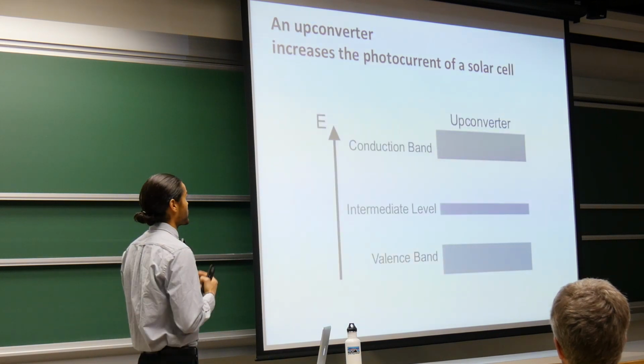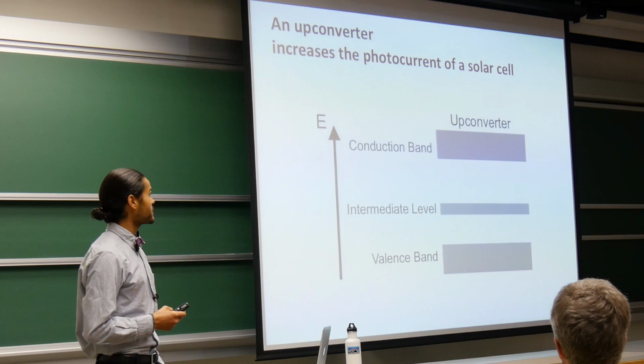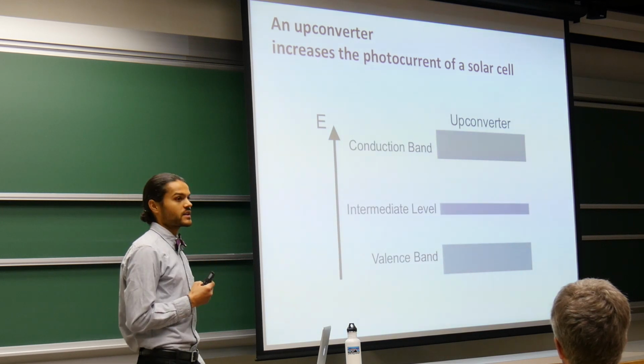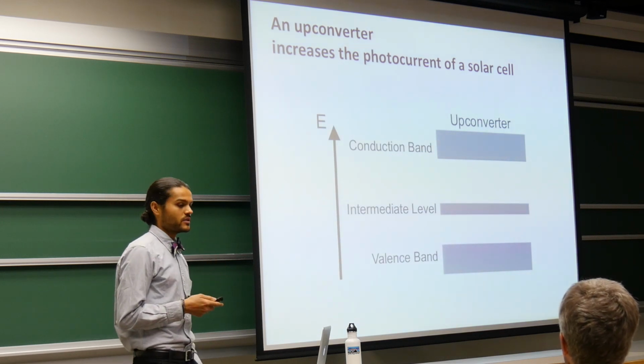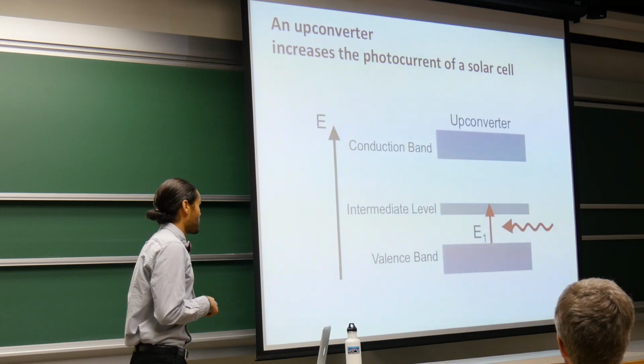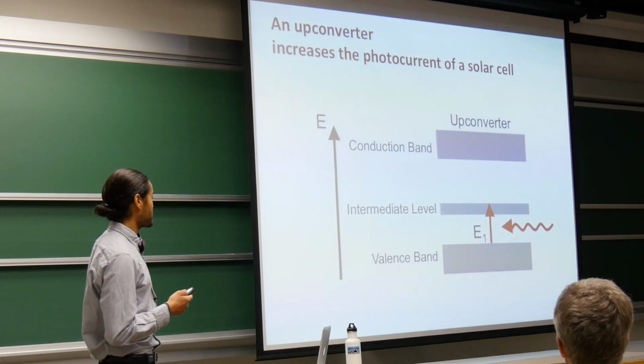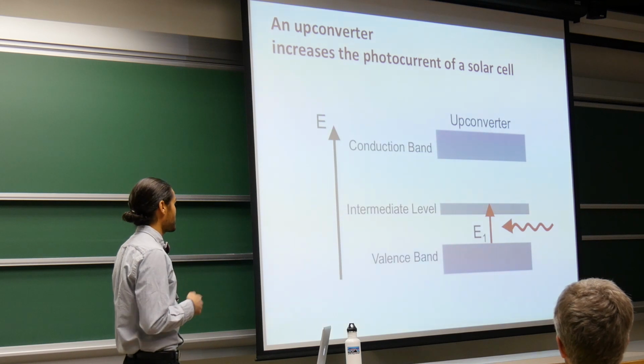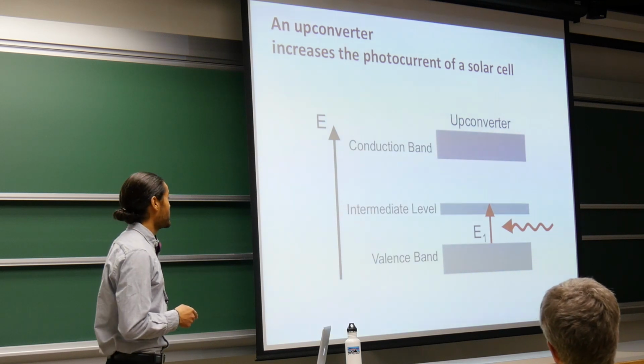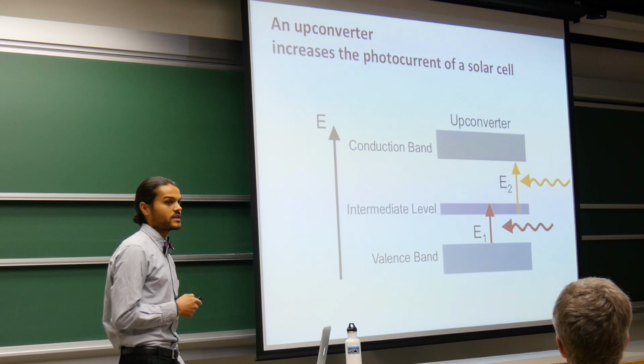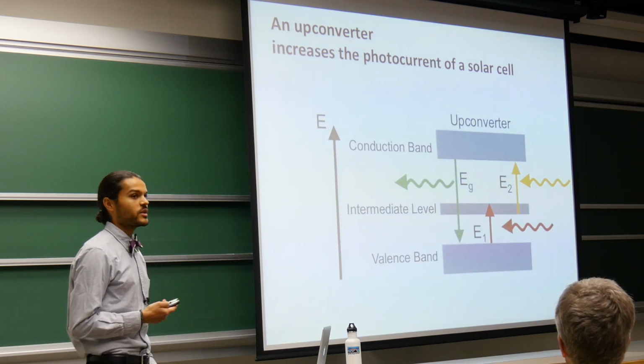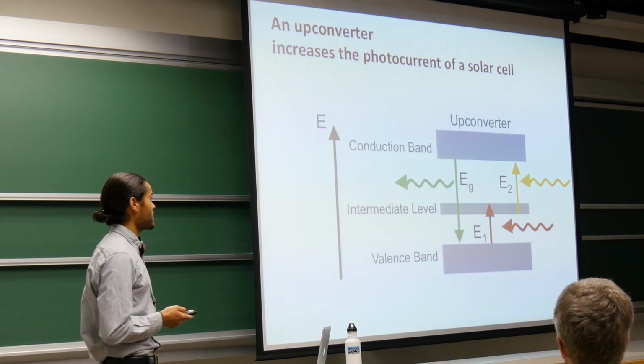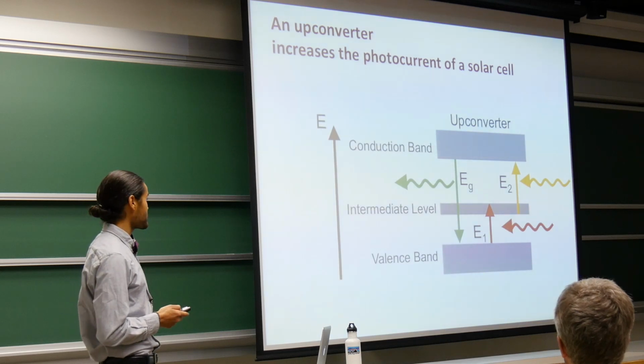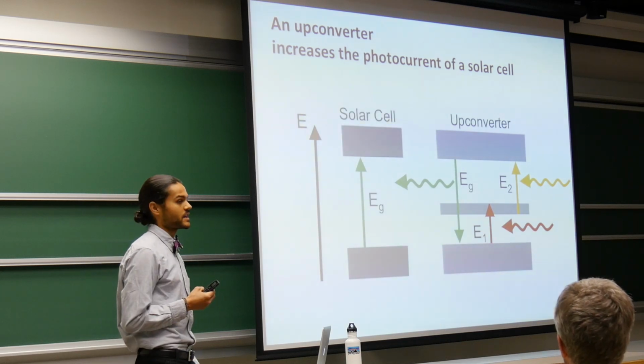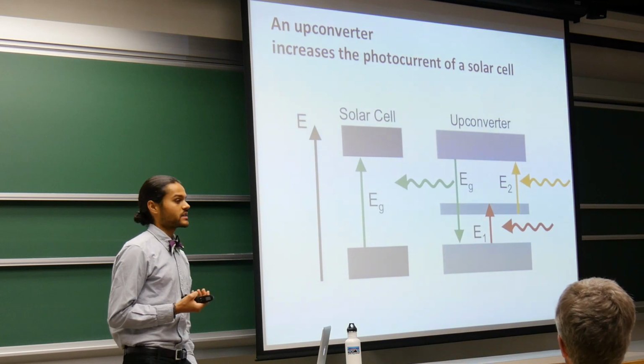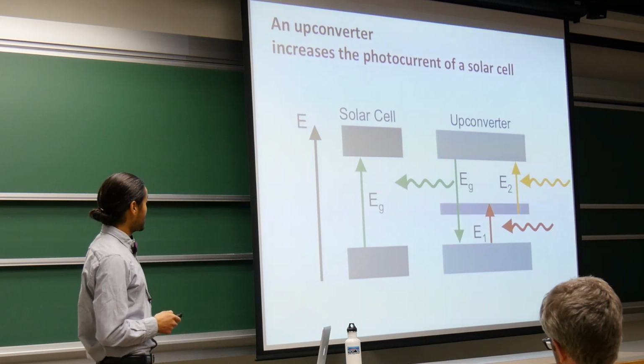So how does an upconverter work? Well, most upconverters can be described by a three-level system where we have, again, a valence and a conduction band, but with an intermediate level in between. So first, a lower energy photon is absorbed and excites an electron from the valence band into the intermediate band. A second photon excites it again into the conduction band. And finally, a radiative recombination event across the band gap results in the emission of a photon with a higher energy. If the energy levels are matched up, this higher energy photon can actually be used by the solar cell.